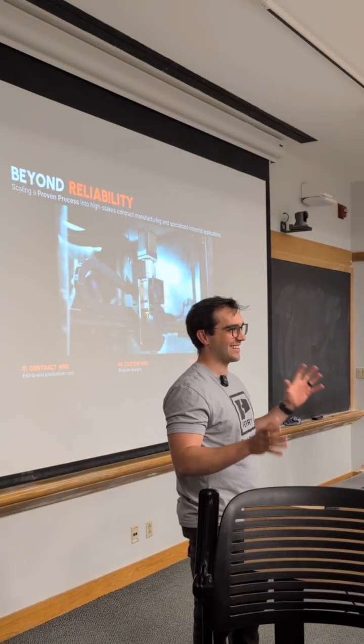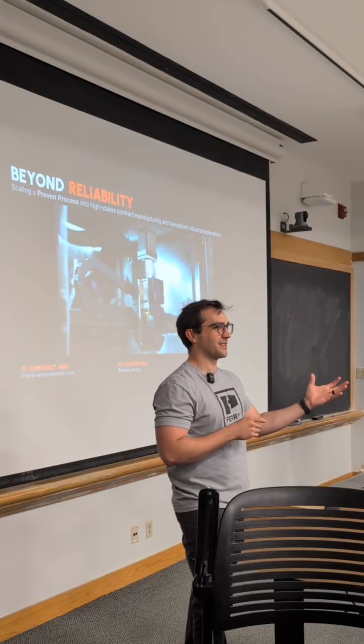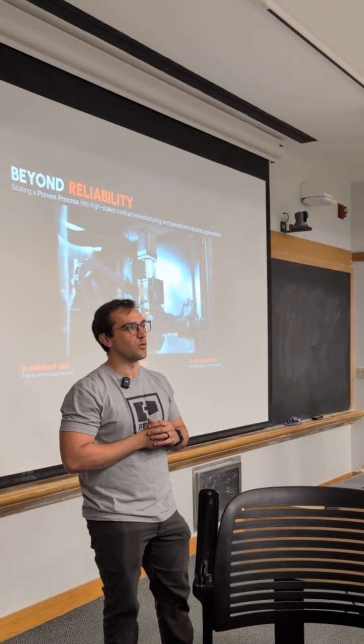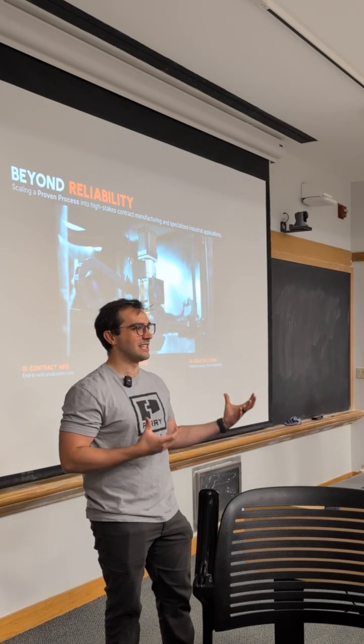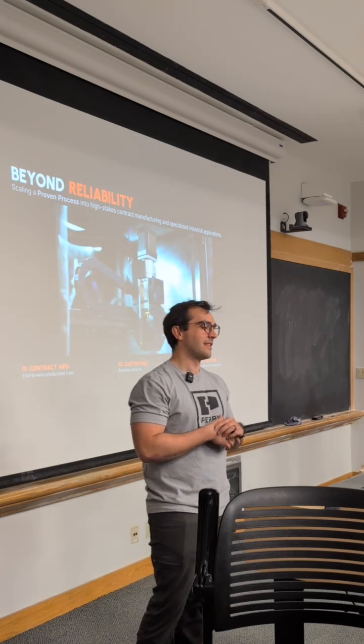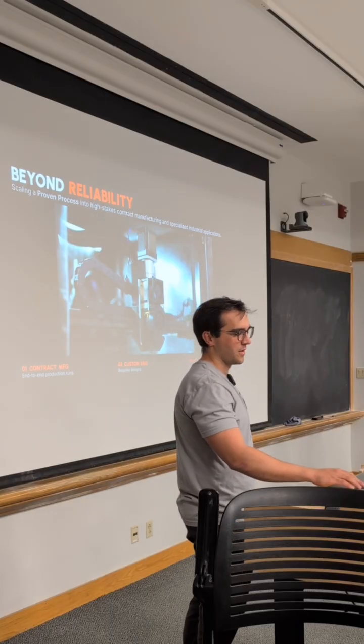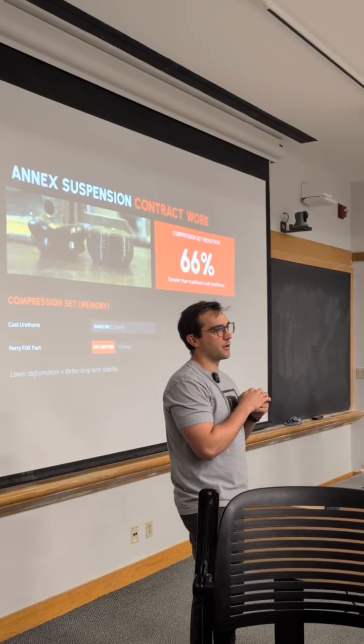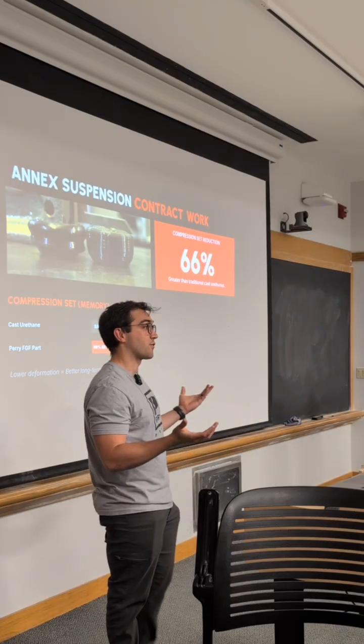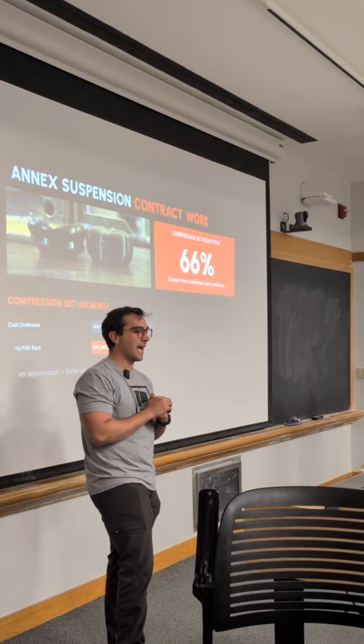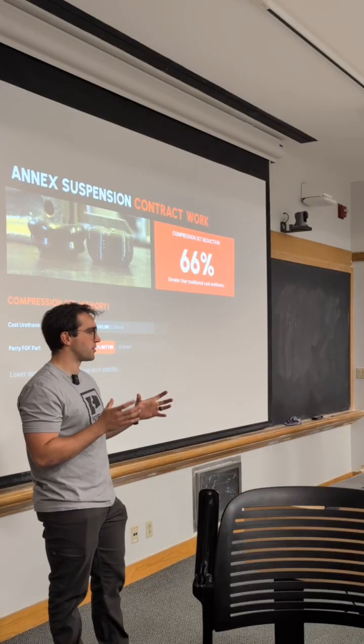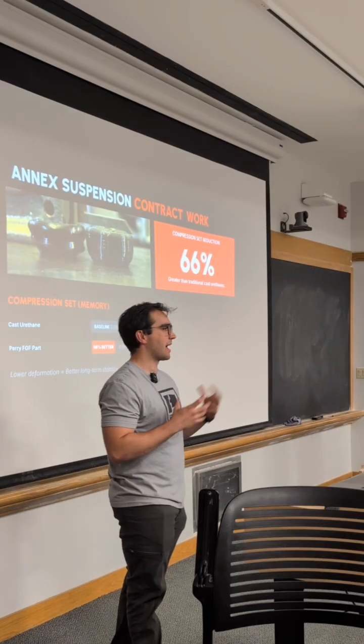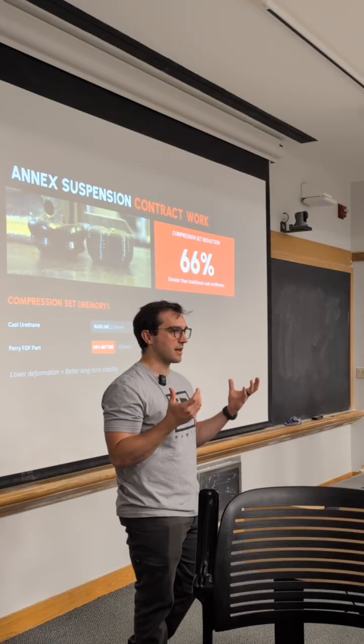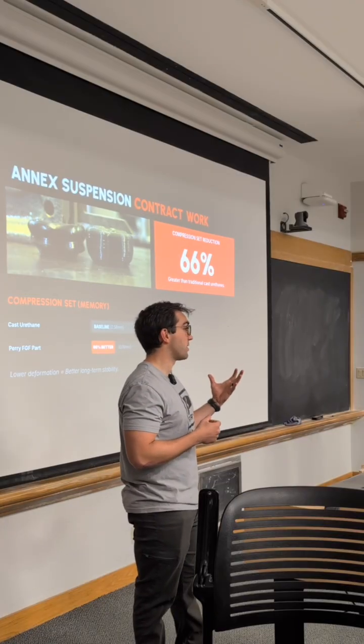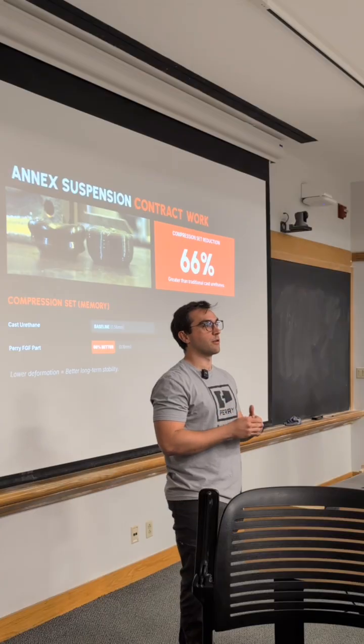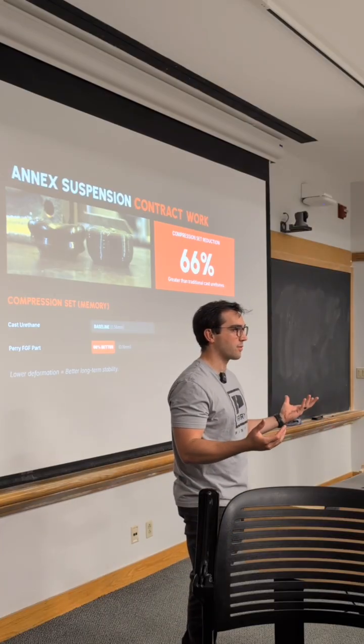A couple of cool use cases. We have a bread and butter product, but we've had a couple of cool opportunities to work with people that are pushing the limits of what you can do, and they've trusted us to try some of this stuff. So we're actually an OEM supplier for a company called Annex Suspension. They make suspension parts for track cars. They had a cast urethane bushing in their coilover stack. Cast urethane is a 2-part material: you mix them, they set, and predominantly people think that cast urethanes are always going to be better than a 3D printed part because 3D printed parts have layers.